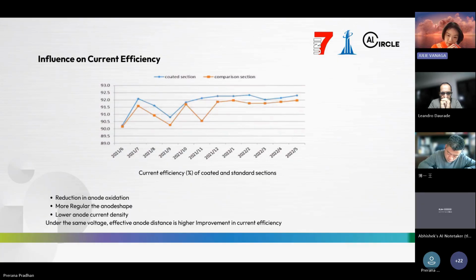By reducing anode oxidation. The anode shape remains much more regular with the coating protection, and the anode current density is lowered. Under the same voltage condition, the increased effective anode cathode distance allows the electric current to be used more efficiently rather than being wasted on resistance or side reactions. The test results show a clear and consistent increase in current efficiency for the coated sections. This means smelters can produce more aluminum with the same amount of electricity, directly boosting production efficiency and output. And this is quite beneficial for those smelters in the Middle East. And let's turn to the next page.